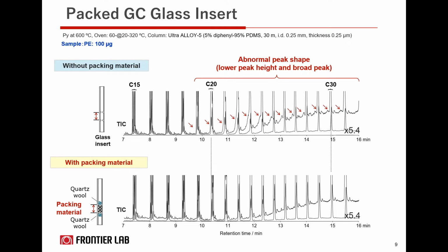Now moving on with another part of the complete solution for microplastics, the packed GC glass insert. We developed a packed GC glass insert, pretty much your liner for your GC, to improve the peak shape of the pyrolysates generated from microplastics. In addition to a better peak shape, the packed GC glass insert can improve the accuracy of your qualitative and quantitative analysis of a specific plastic in a polymer mixture sample using F-Search MP 2.0 software. And you can see an example here of how the abnormal peak shape and the lower peak height are improved when you are using that packing of the GC glass insert.